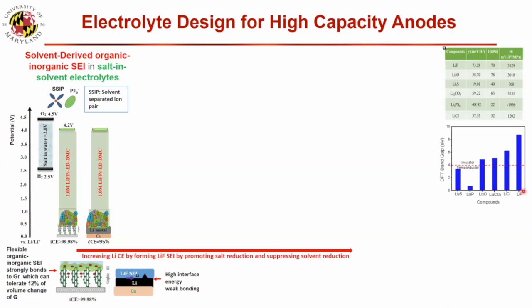And if electronic conductivity is the lowest, when they form SEI at a very thin thickness, they will block electrons. Very thin SEI translates into a very high first cycle coulombic efficiency. Third, if by chance we can form lithium fluoride on the cathode side, you see the stability window of lithium fluoride is highest compared to others.